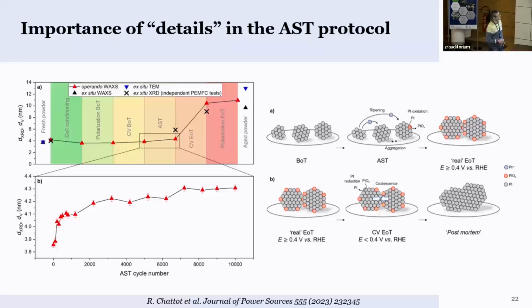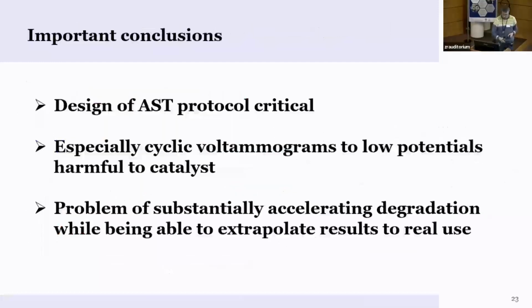Although the electrochemistry shows that you reduce them, some of the atoms might still be oxidized, and that kind of prevents the melting together of the particles. But once you go to low potentials, then they basically start to form a new crystallite size. So these details in the protocol really have a very large influence on the result. And we actually don't really know what is the right way to design a protocol that can predict lifetimes in the order of 10 years. So that's a huge problem.